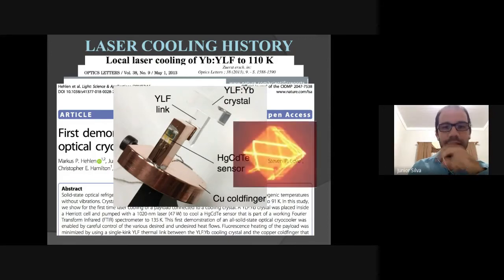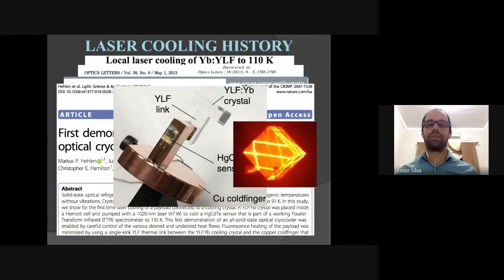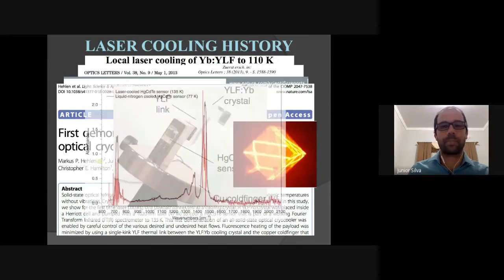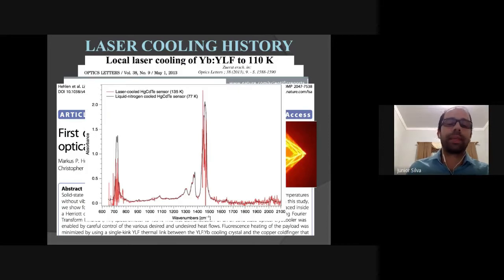The next figure here shows how they cool the crystal in a real situation. Because when we study this material, we just use the laser to go through the material. In this case, they use the laser to create a kind of trap inside the material, going to total reflection inside the material, to be completely absorbed by the sample, the light. And here we can see a graph using the crystal and using liquid nitrogen as classically is done. There is a region here from 800 to 1,400. That's okay, but the other part is not okay. We should cool more, okay? But this was the first experiment.